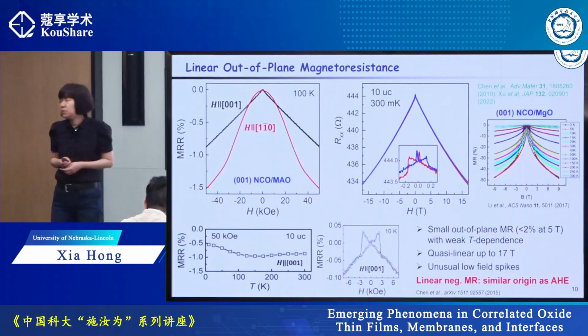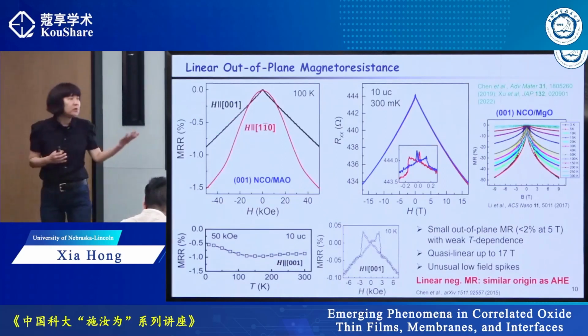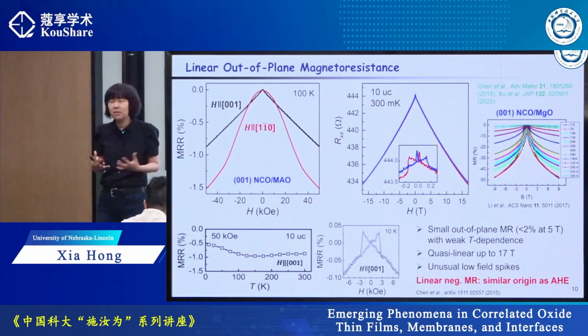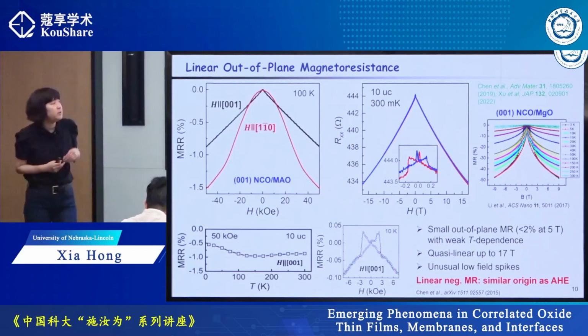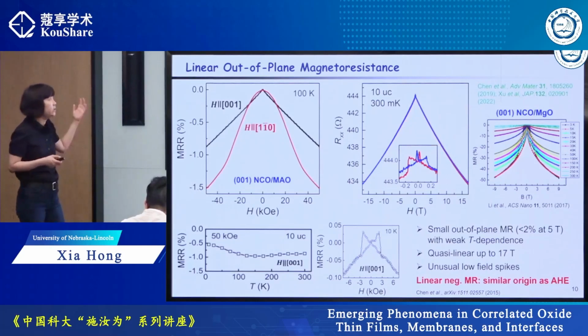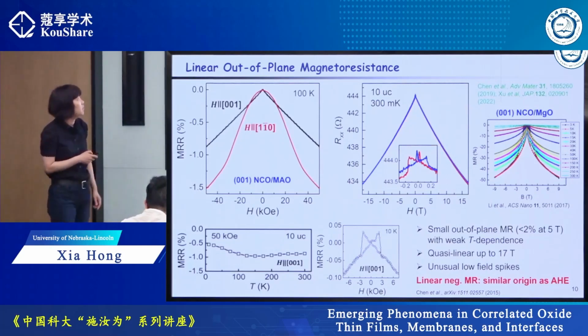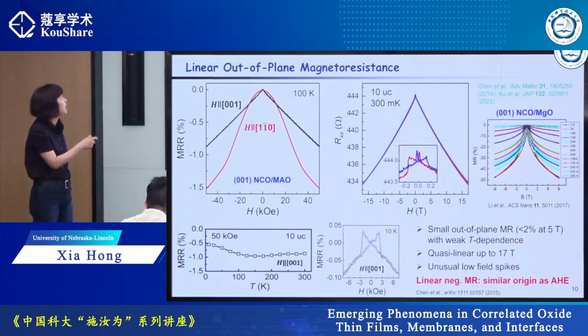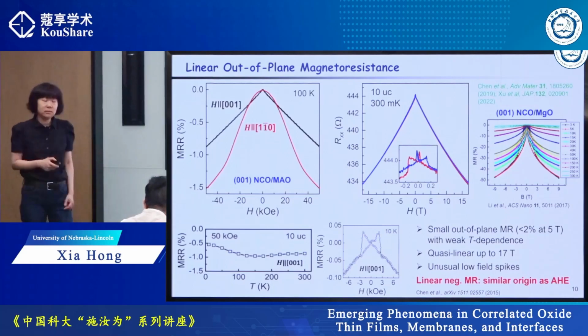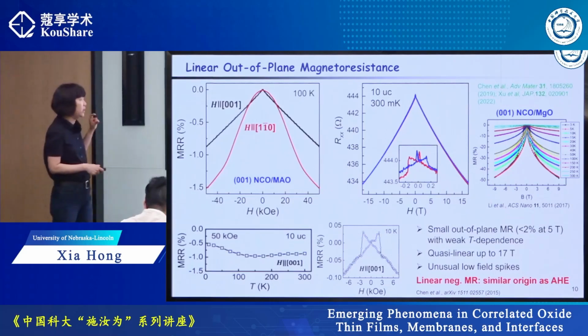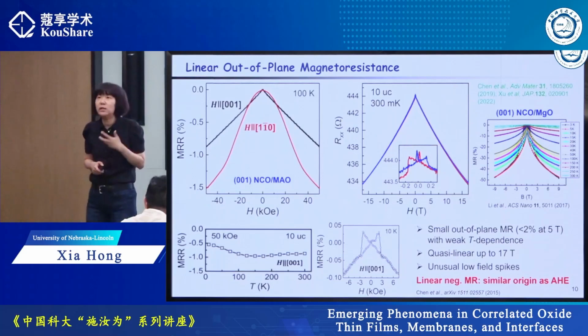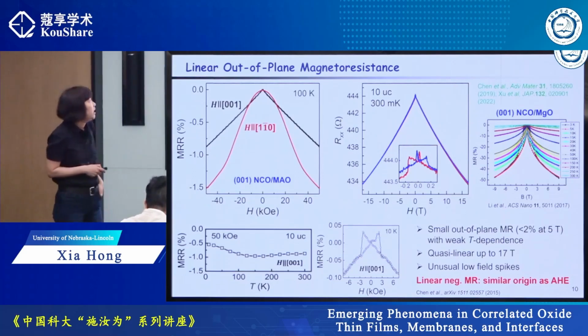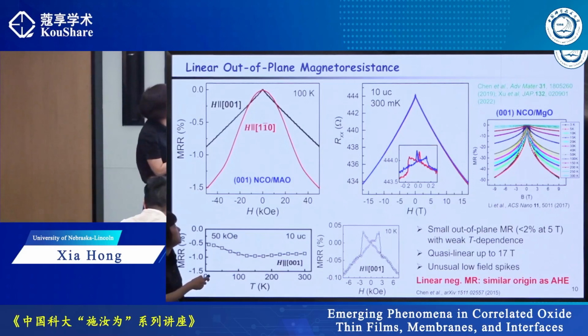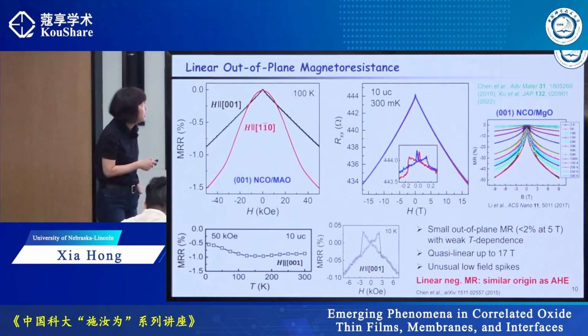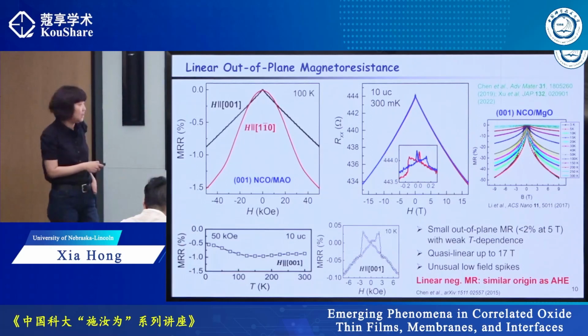So now what we find is not only we can have the very appealing magnetic properties, its transport property is also very interesting. What's shown here is the magnetoresistance of the film. And you notice that unlike most magnetic oxides, it has a linear magnetoresistance. And the magnetoresistance is very, very small. It's weakly temperature dependent. This is because we have very, very nice films. And such a linear magnetoresistance can be sustained down to 300 millikelvin, up to 17 Tesla.